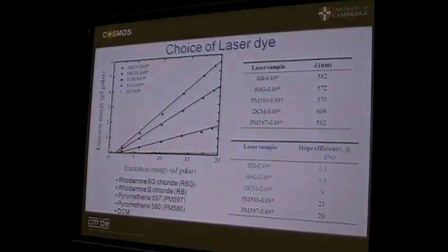And there you have it. A lot of papers in the literature talk about DCM. Okay, that's one of the fluorescent dyes. We found for these kinds of lasers that the pyromethenes are more efficient systems. So try to compare like for like. Take the same host, E49, just as a workhorse, just to see the operating parameters. You see quite a big difference between the lasers, the output lines are about the same wavelength, thereabouts. But you see a very big difference in slope efficiency.